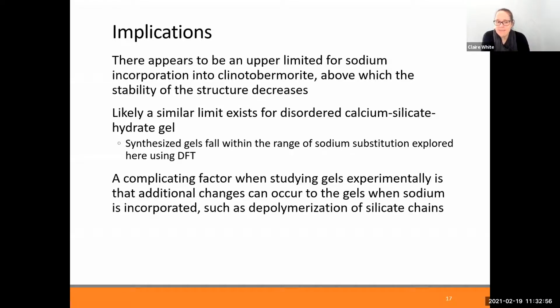Now, one thing that's a complicating factor is that we know when you incorporate sodium into the gels experimentally, you don't have exactly the same bonding environment in the substituted gels that you have in the original gels. Specifically, we know that the silicate chains that exist in the gels will change based on the amount of sodium that's incorporated. We wanted to get a better sense of this from an experimental viewpoint. So what I'm going to show now is sodium incorporation into synthetic calcium silicate hydrate gels and the impact on things like the chain length and nanocrystallinity and some other properties.